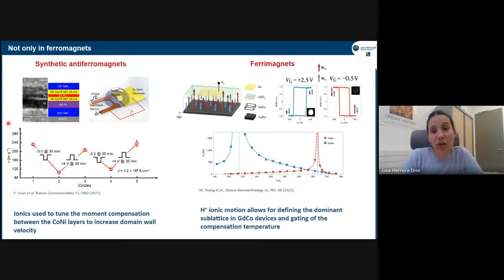And this, of course, can be done as well in natural ferrimagnets. So here they showed that they could control, well, here it's gadolinium cobalt. So here there are really two sublattices that are aligned against each other. And then there is a dominant magnetic moment either from the gadolinium or the cobalt. And then the electric field could allow to go from cobalt dominated to gadolinium dominated. And here they measure the typical signature of a ferrimagnetic system, which is the compensation temperature.